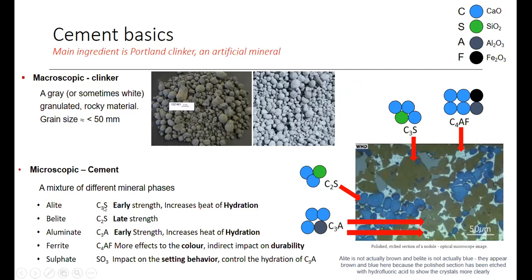C3S in cement chemistry is called alite. It delivers early strength and increases the heat of hydration. C2S is belite, which delivers late strength. Aluminate delivers a small amount of early strength, but it acts as an initiator of the hydration process and delivers more heat of hydration. Ferrite has more effect on the color, and very recent studies found it also has an indirect impact on durability because of some process engineering parameters dealing with clinker formation inside the kiln. I will not discuss it here, but yes, there are some impacts on durability as well.